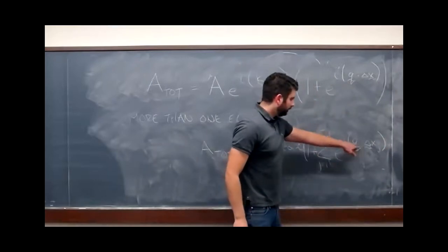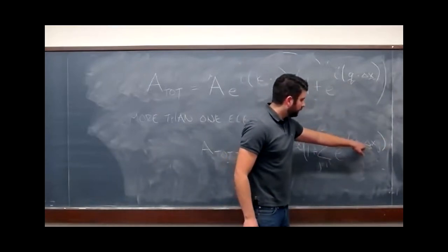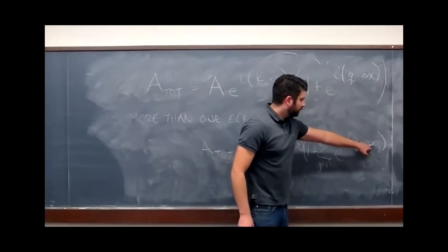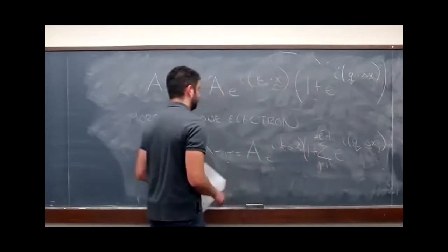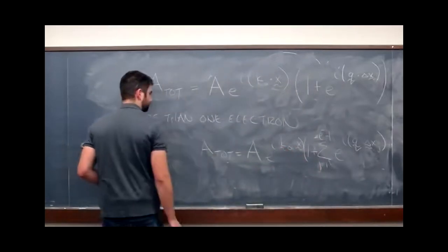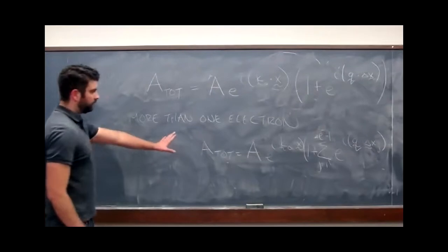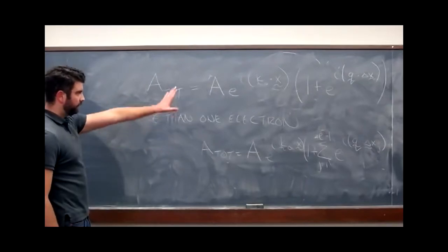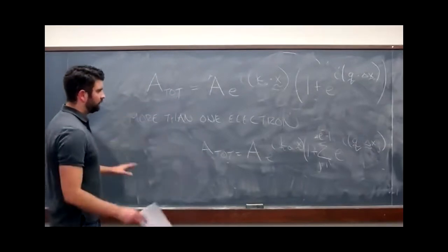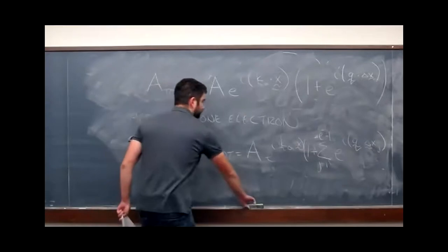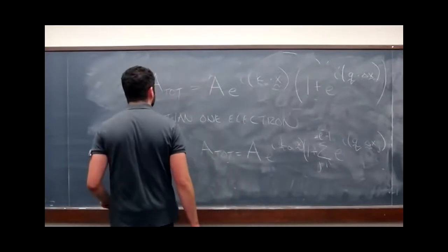So this here is just the scattering vector dotted with the position shift of the current electron, delta xj. So we can calculate the total scattering amplitude that we'd observe from any collection of atoms if we know all their positions in space relative to a reference electron.